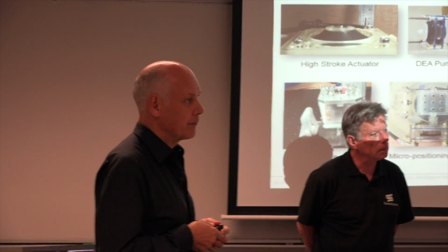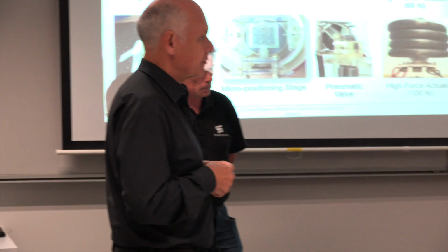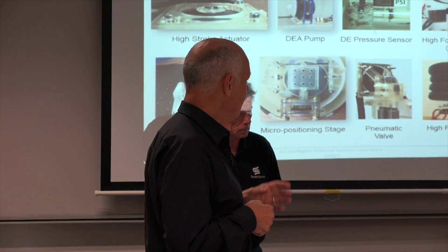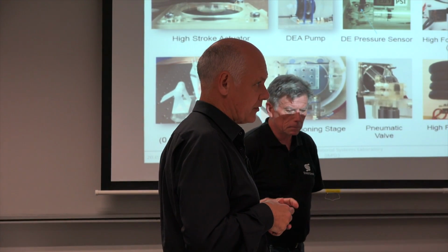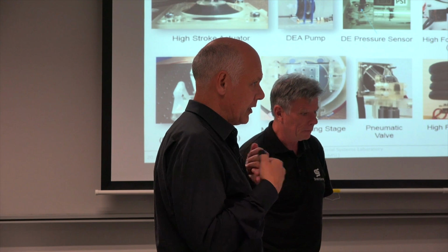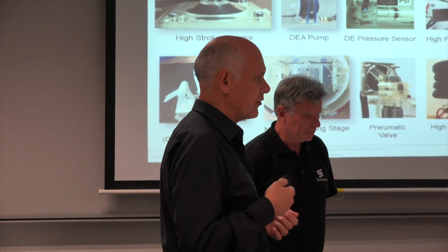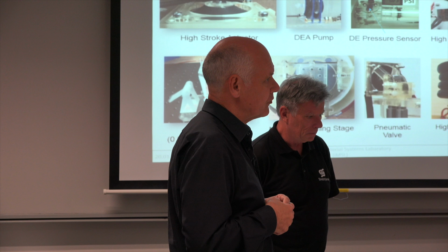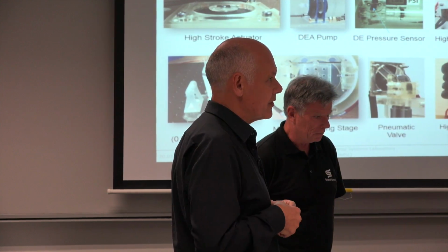Peter? Well, what's the efficiency of the electrical to mechanical conversion with the dielectric elastomers? With a dielectric elastomer, it can be up to 80 to 90%. A lot of it depends on the electronics that we haven't talked about a lot. You have to generate high voltage, and the way that you generate the high voltage is one of the biggest contributors to your efficiency.